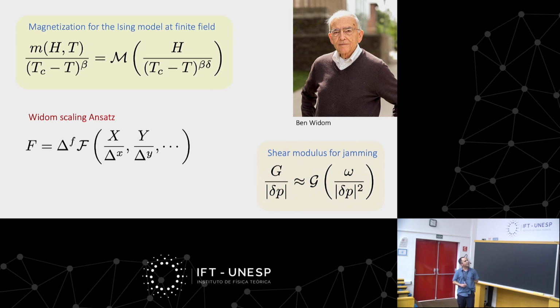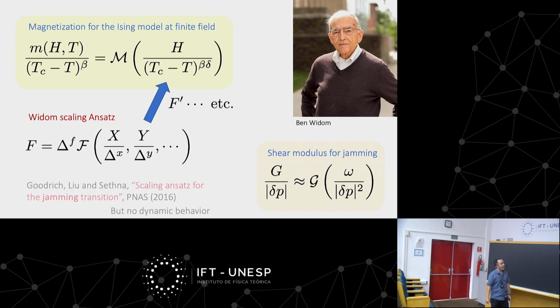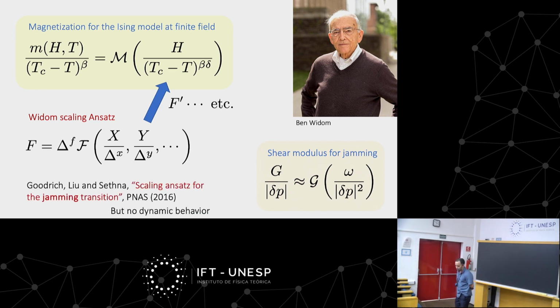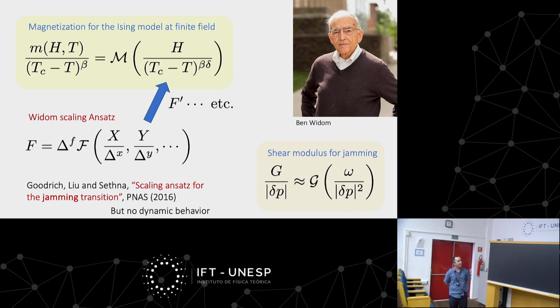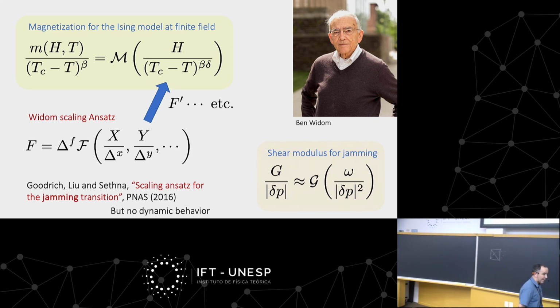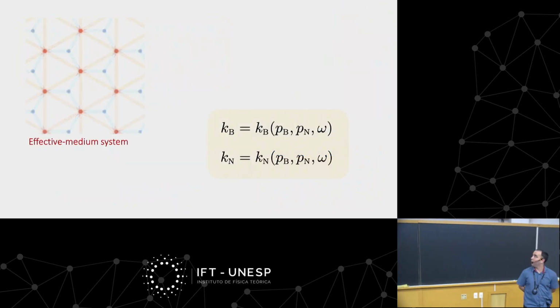And it's nice because if you do that, you can calculate all other scaling forms by taking derivatives of this free energy. For instance, you can take the derivative of the free energy on the magnetic field, you get the scaling form for the magnetization, and so on. And you can get lots of results just from this simple scaling analysis. And people have done that. My colleagues Goodrich and Andrea Liu and Jim Sethna have done the same kind of analysis for jamming, based on some ansatz for the free energy as well, but they didn't have the dynamic behavior. So one of the things that we did was to extend this in order to also include dynamic behavior in this system.